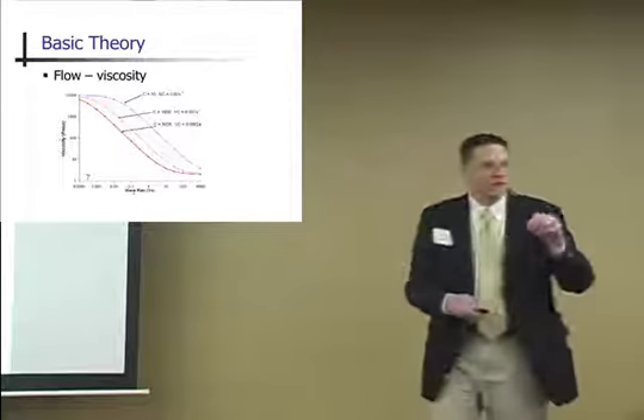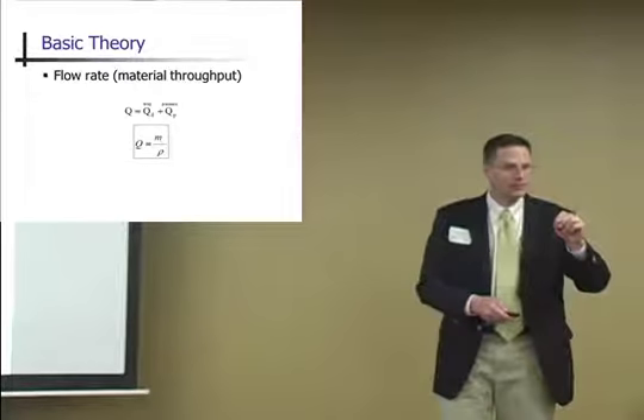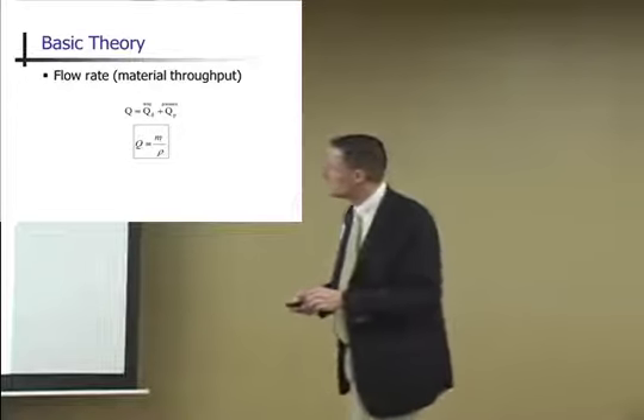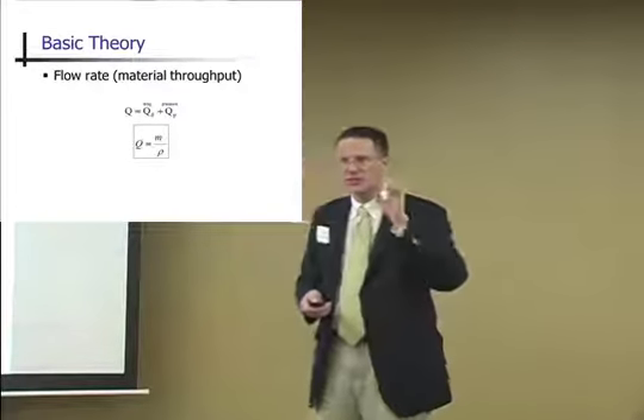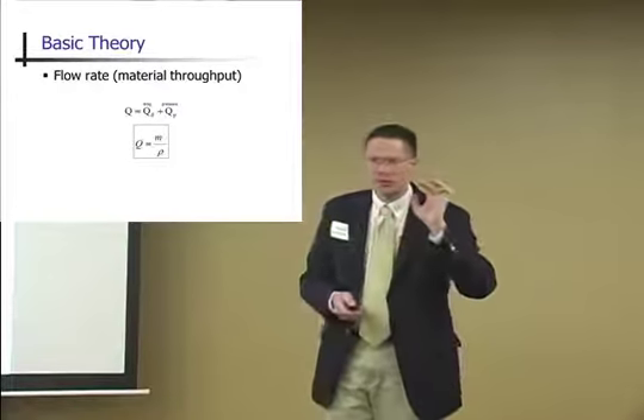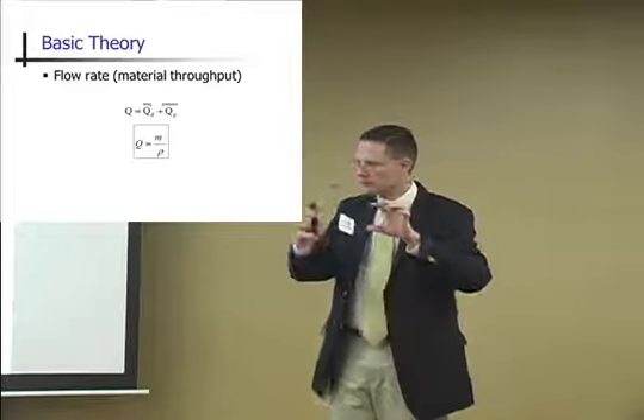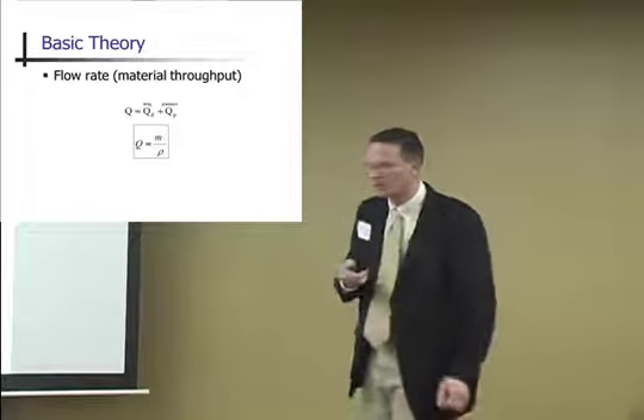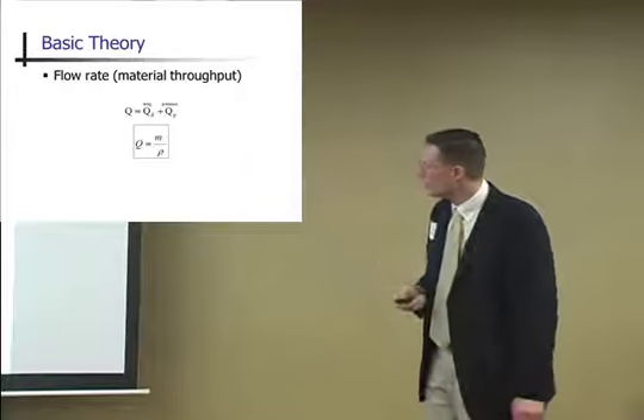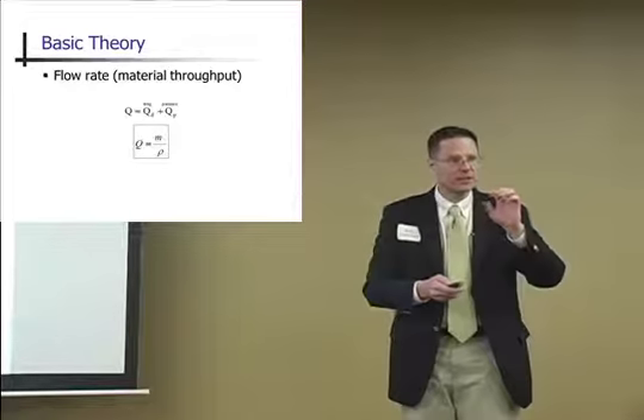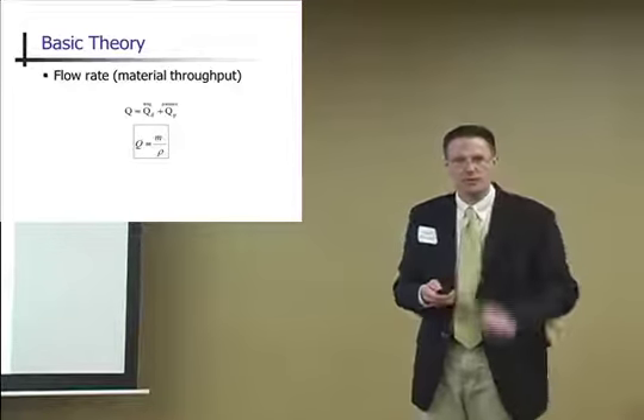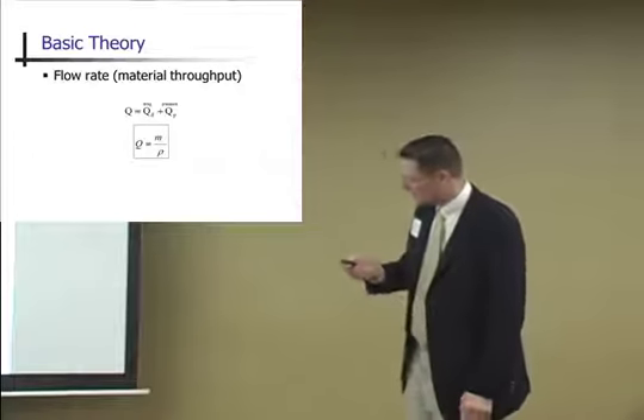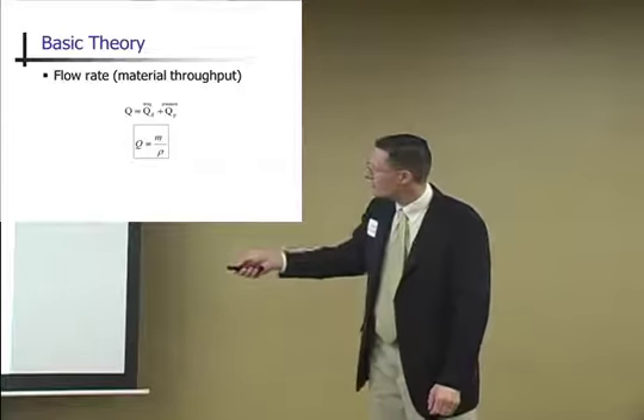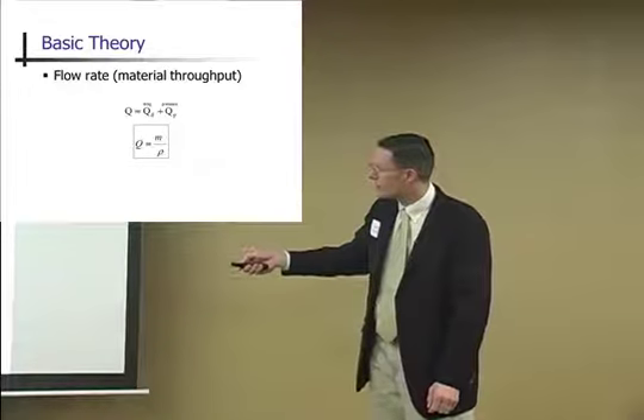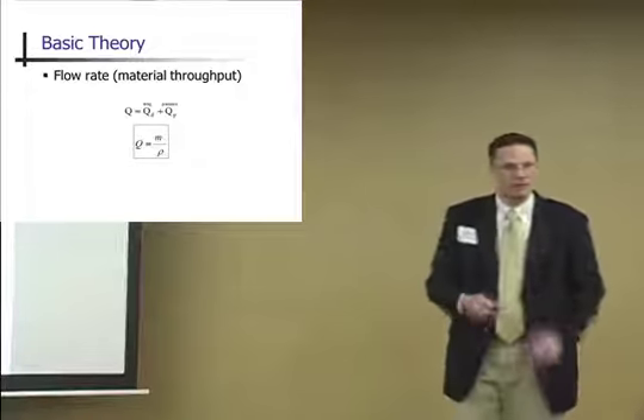So that impacts your flow rate through your extruder. And basically, what pushes that material through the extruder? It's the friction with the screw and the resistant friction against the extruder wall, the barrel wall. But it's also the pressure that's building up. It's also pushing that material along. So the best way to quantify your flow rate is your mass flow rate divided by your density. The density of those pellets.